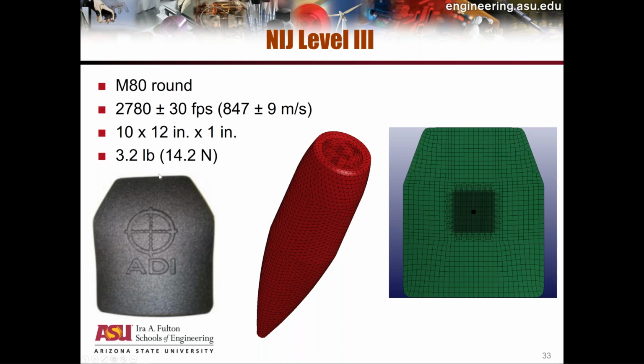This was able to easily defeat 6 shots of M80 round shot at roughly 2,780 feet per second. So there are 6 shots that take place in this armor, and the computer model that we used was only for 1 shot. We were reasonably sure that if you are able to defeat that shot using the actual produced armor, then it would take care of 6 shots, and that was the case. And it was relatively thin, 1 inch. This is hard armor. There are other types of armor that defeat lower threat levels, which are soft armor.